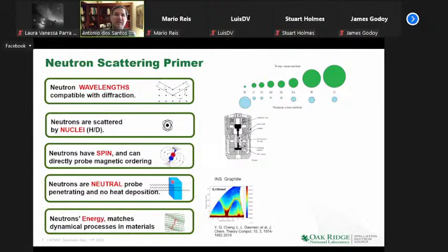Now, finally, and this is really also unique, is that neutrons can be produced with energies, because of their mass, that match dynamical processes of materials. What do I mean by this? Phonons, like cooperative oscillations in the lattice, but also rotation modes of molecules, dynamic energy barriers for diffusion, for instance. So you can actually have neutron beams that match those, and so you can interrogate directly that energy.